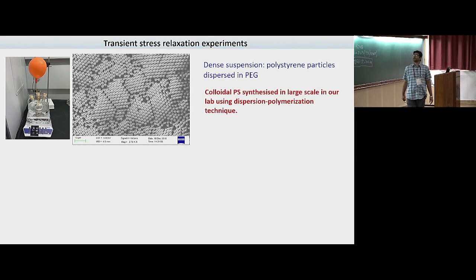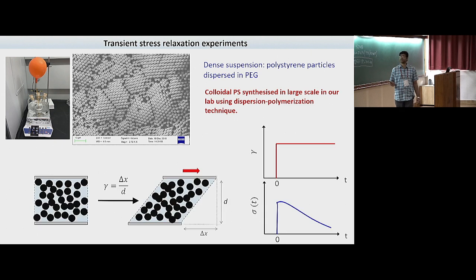This is the system we study. We synthesize monodisperse polystyrene particles, with a diameter of approximately 2.6 micron, in large scale in the lab using a technique called dispersion polymerization. We disperse them at a very high volume fraction in a non-evaporating solvent, PEG. And this is the schematic of the experiment.